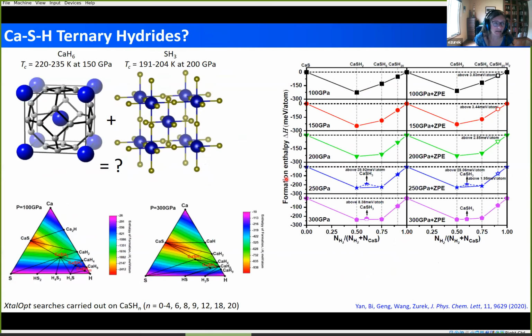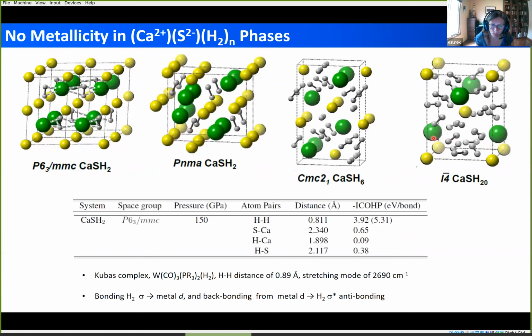Next, I'll mention briefly that in the sense of ternaries, we also considered what would happen if you mixed something like calcium H6 with sulfur H3. We know that calcium H6 was predicted to have a very high TC, and this was recently measured and reported by two different groups. Generally speaking, most of the phases we found when mixing an alkaline earth metal with sulfur consisted of something like calcium 2 plus S2 minus with a bunch of hydrogen added to it. These are not going to be high temperature superconductors because they are basically going to be typically insulating.